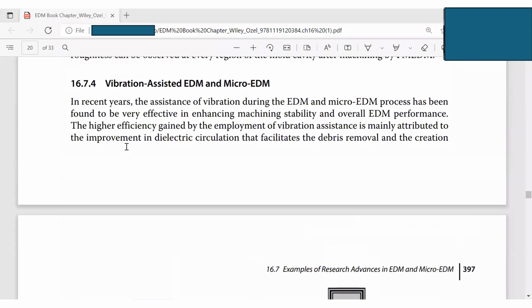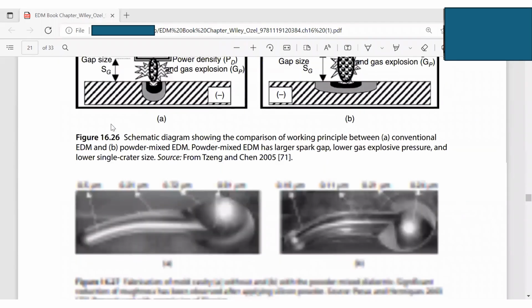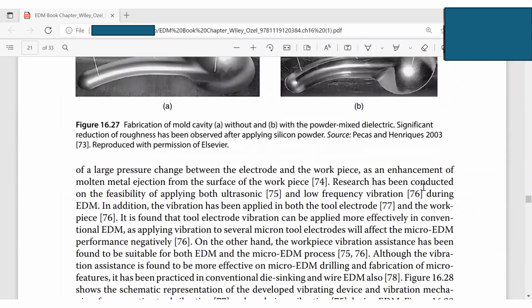Another thing is that with vibration assistance, we can change the microstructure of your material after finishing. And I want you guys to write down, okay? Research has been conducted on the feasibility of both ultrasonic and low frequency vibration during EDM. I want you to write it down: the vibration assistance can also change the cooling rate of the dielectric fluid on the machined surface. As a result, microstructure or nanostructure can be changed. That's done.